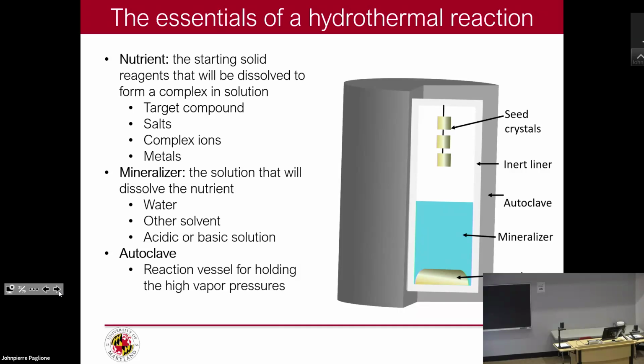Acidic or basic conditions. For example, on our iron-based superconductors, we almost always work at pH 14, and no less than that. So super basic conditions, because under acidic conditions, you generate a lot of defects in these materials. Why? Because, as Hana was alluding to, we have these Pourbaix diagrams, these diagrams about pH. They tell us at what concentration we'll have oxidized versions of different elements.